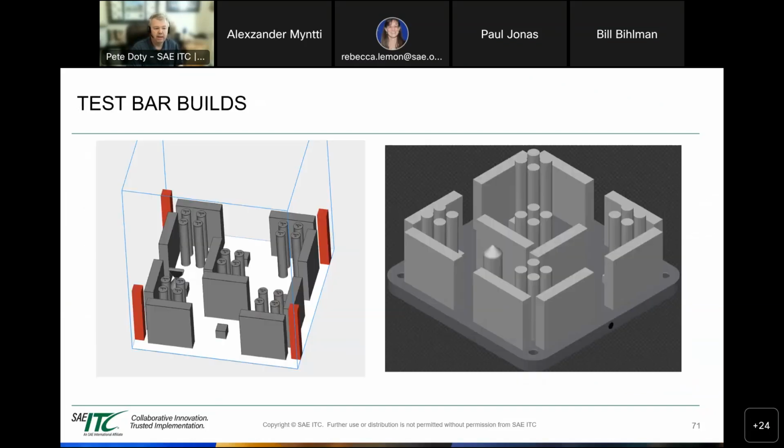So what normally happens is that for particular materials, you do test builds in a variety of axes. These are some representative builds for laser powder-based fusion parts, where you build cylinders in the vertical direction, and then in X and Y different directions, you build essentially walls that'll get cut down into bars, and that these will then be machined into test articles and sent to a mechanical testing lab that will go ahead and break them and determine the tensile strength of the material that you've built.